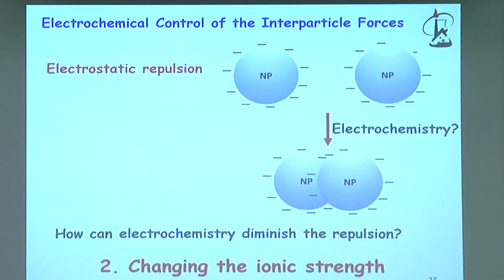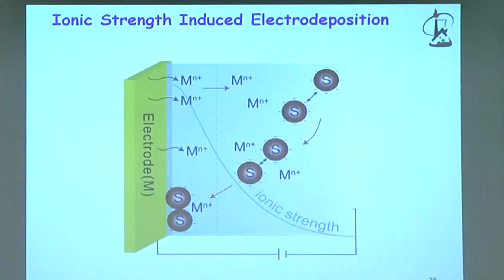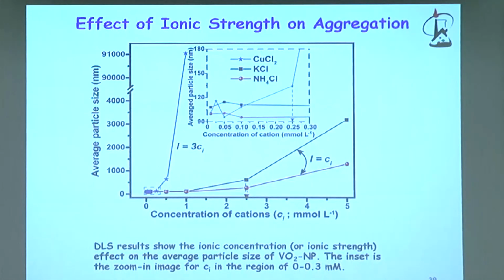So how can we, by electrochemistry, increase the ionic strength? And to do that in a very simple way, and not change the pH, we simply took a copper surface and we pulsed it with a short pulse of positive potential, which generated a flux of copper ions. We generated a flux of copper ions on the electrode surface, increasing the ionic strength and causing the deposition of the nanomaterials.